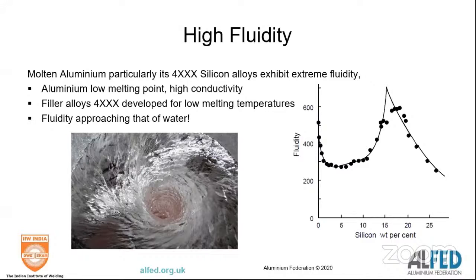The 4000 series of aluminium are based on silicon. So silicon is the principal alloying element. And the reason they were developed is you've got parent metal alloys with high thermal conductivity and low melting point. If you try and weld them, you just end up with a pool of liquid. By developing the 4000 series, with low melting points down to the low 500s and some of them down to the high 400s, now you can melt your filler metal with good fluidity without melting your parent metal. So it's an important property.